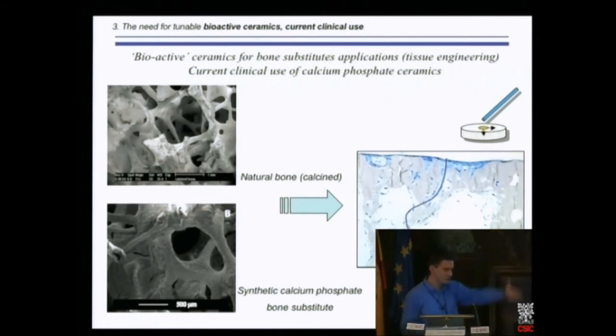So in this picture, it is a cross-section of bone substitutes, and we have put some osteoblast cells, because these are the osteoblasts that we want to study. And these cells are in this cross-section in blue. So we have put some cells at the surface of such substitutes, and after 21 days, what we observe is that all the surface is covered with these blue dots. These are cells which have been colored. So all the surface has been covered by these cells, and more important, the cells now have proliferated inside the bone substitute. What you see here in blue is the path followed by the cells among the interconnection between pores. So of course, interconnection between pores is really important for this kind of material. So the cells are able to pass through the interconnection, and then they adhere to the surface of the pores.